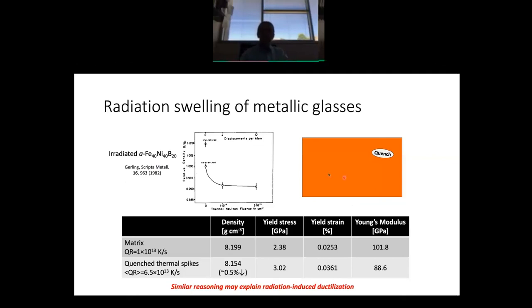And unlike in the case of crystalline metals, the swelling saturates. So this is experimental findings from a paper from 1982, published in Scripta Metallurgica, that shows you the behavior of the density of an iron nickel boron metallic glass. So this is the starting density, relative density 1. After a certain neutron fluence, the density drops by about 1%. Okay, so the glass swells. But as you continue to irradiate, it saturates, right? So it doesn't swell without bound. It just swells up to a certain level and then stops.